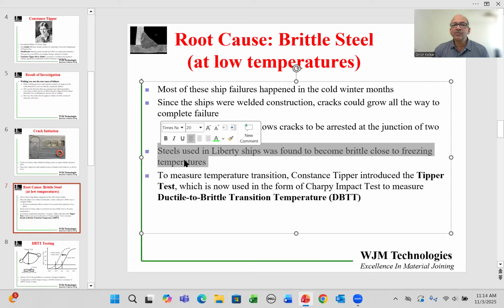So the main issue was, why are these cracks growing so quickly? And she found out that the steels were becoming too brittle close to freezing temperature. So these steels were ductile when measured in the lab at room temperature, but close to freezing point, these steels were behaving in a very brittle manner.